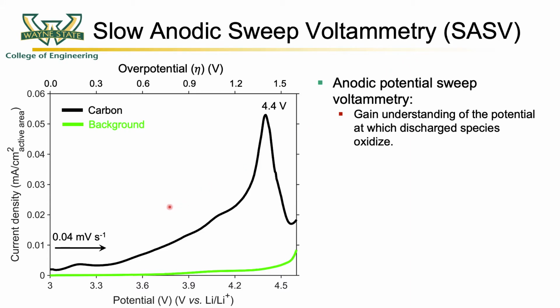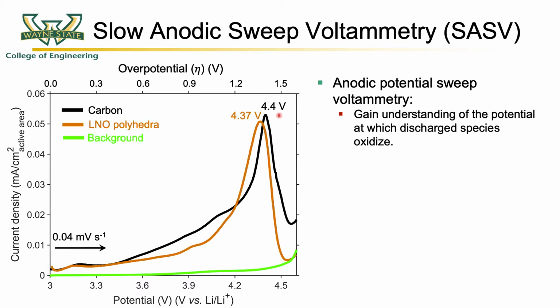What this experiment does is the charge cycle is slowly swept through from the theoretical potential to roughly 4.6 volts while the current is monitored. On a carbon only electrode, a single peak at about 4.4 volts is observed, consistent with our discharge charge studies as shown in the previous slide.